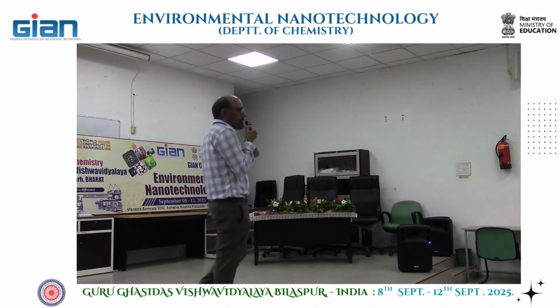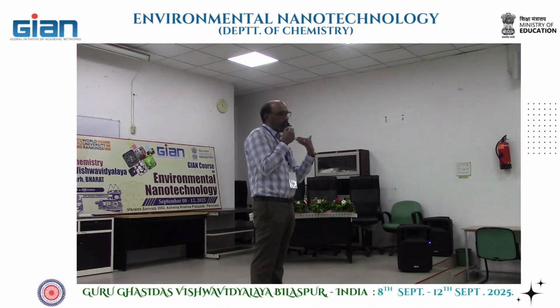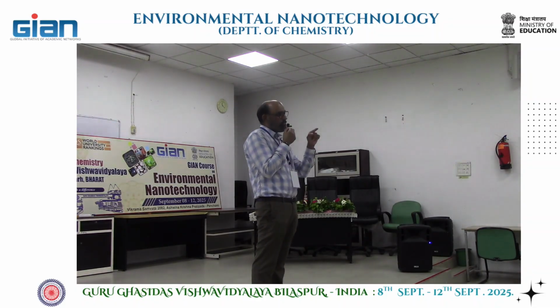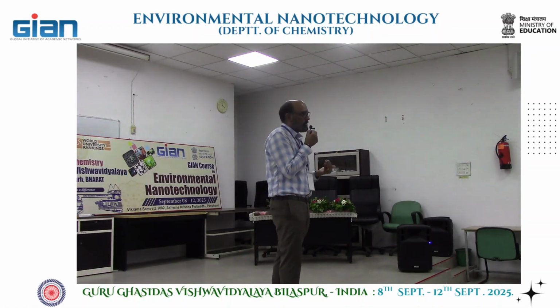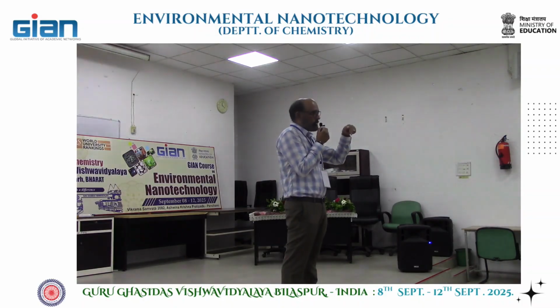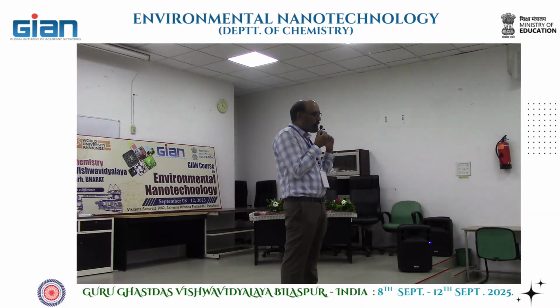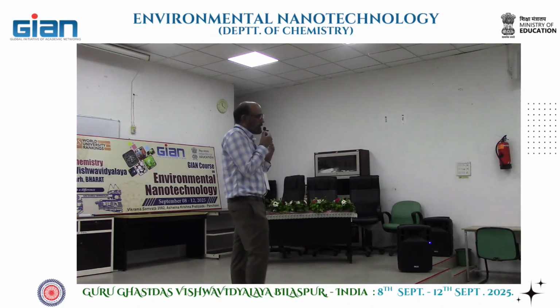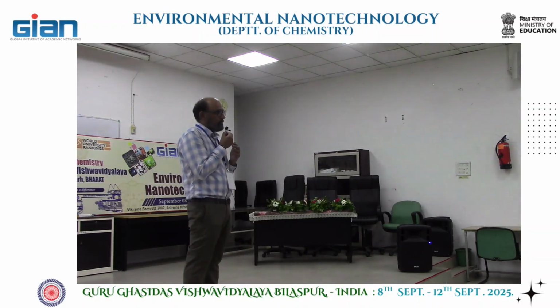Even our lab started doing something like that. For heavy metal adsorption, normal films are not very efficient, but when we do these sacrificial glucose templated films, you have extra pores within the fiber. That's very useful. Nylons and other polymers are very good for this. People have done it, yes. I think they are well-known fibers.